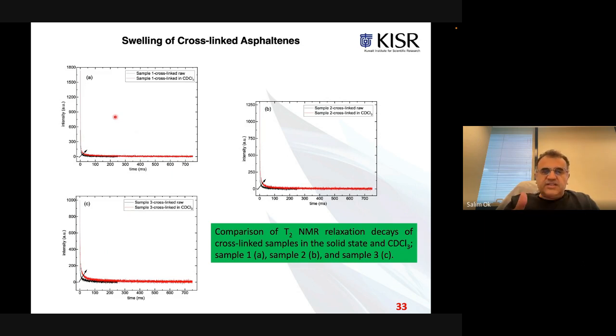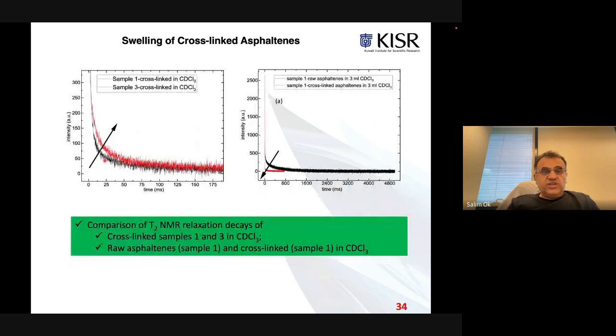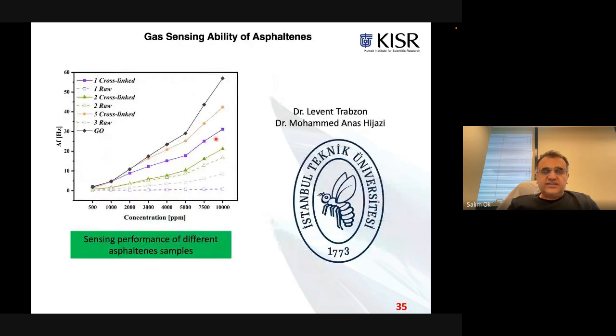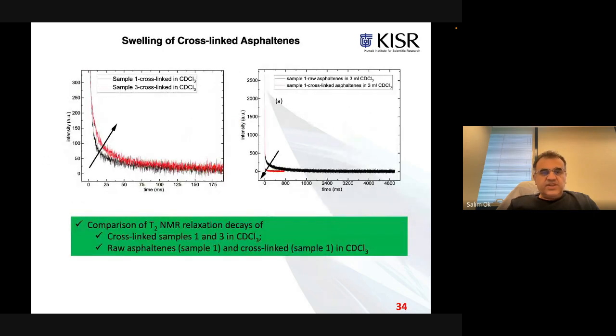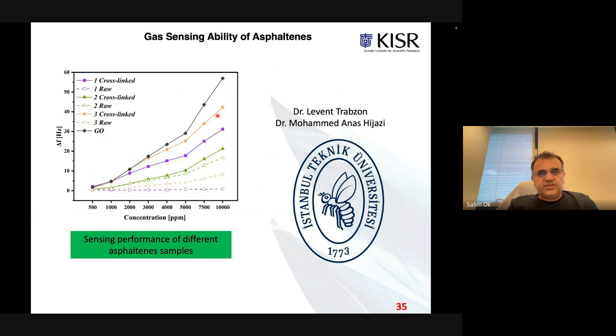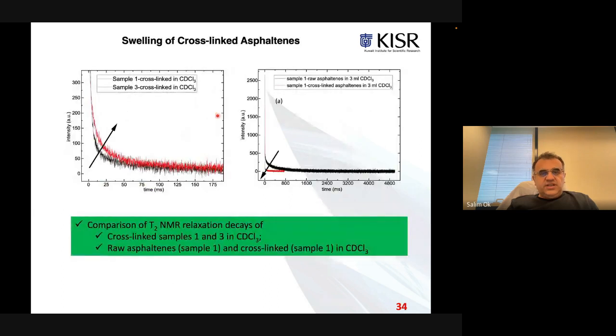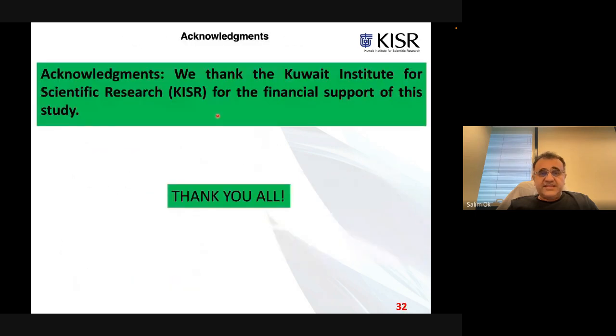This allowed us to focus on the swelling behavior of the cross-linked asphaltenes. Comparing all the samples, sample 3 was able to show higher swelling behavior, and interestingly, the same cross-linked sample 3 with the highest swelling behavior also shows the highest sensing ability towards ethanol and isopropanol molecules. So there's a pretty nice correlation between the swelling behavior of those cross-linked modified asphaltenes and their sensing behavior.